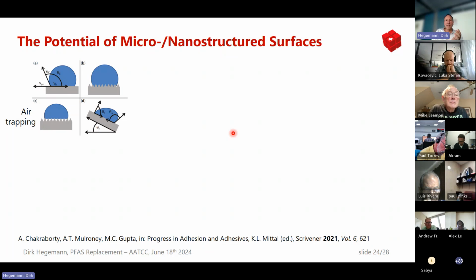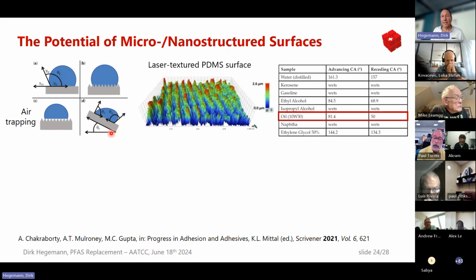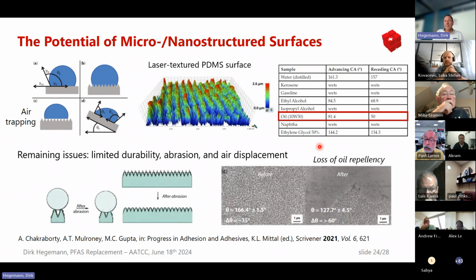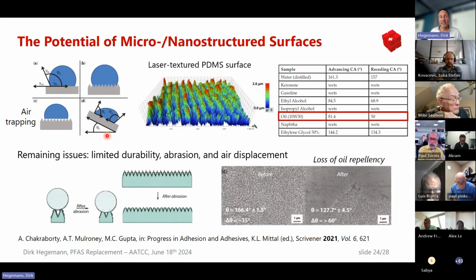Typical approach, when you look at literature, they consider nanostructured surfaces. The idea is that you have air trapping and therefore get a higher repellency. On PDMS, that can be done by laser texturing, and indeed it's shown you have very high water repellency, but also some oil repellency. Also, you repel a few other substances, not everything, but it already looks promising. However, those surfaces tend to be abraded, which is a remaining issue. You have limited durability, and whenever you apply a force, you have air displacement, you're also losing these beneficial properties. And when you have some wear, you then also lose the oil repellent properties readily again.